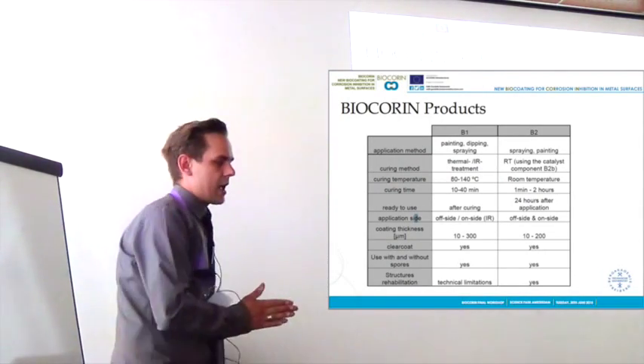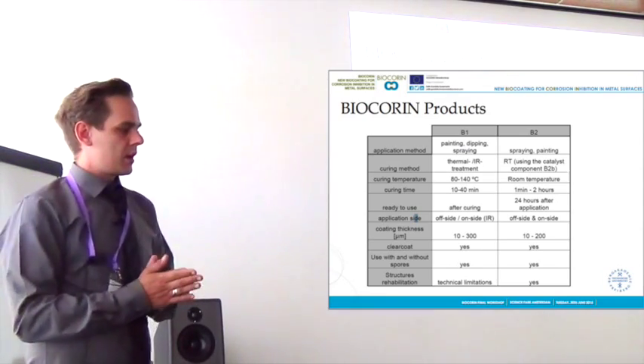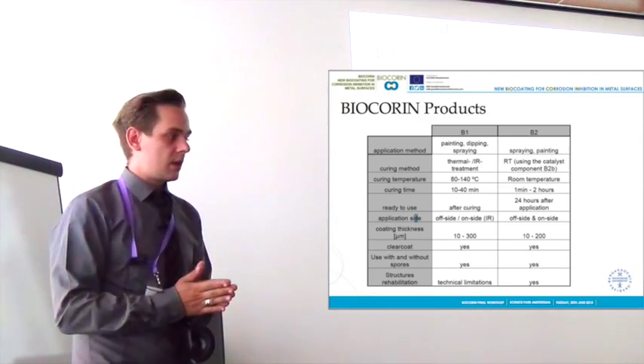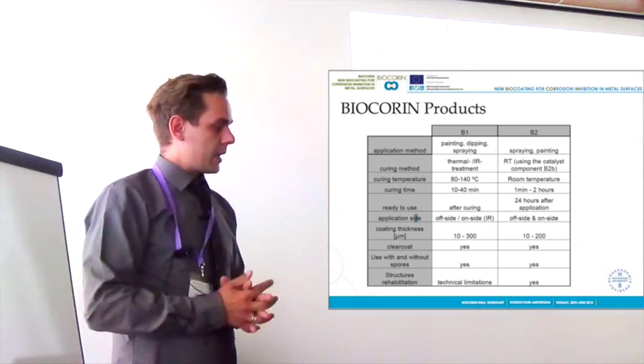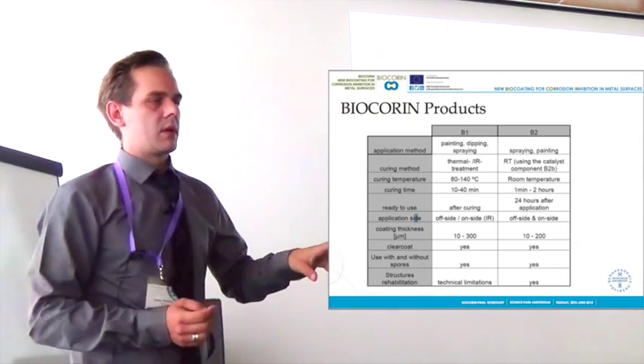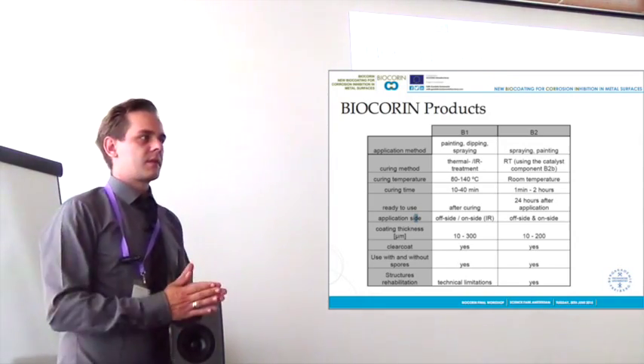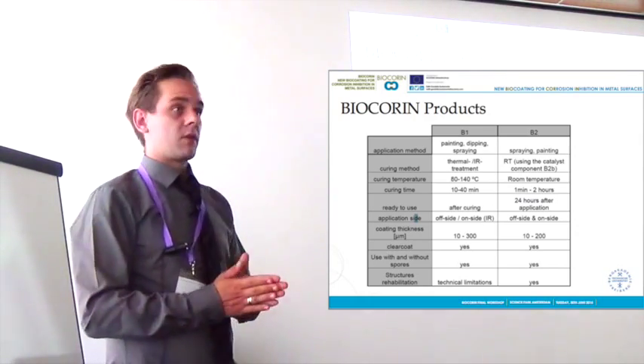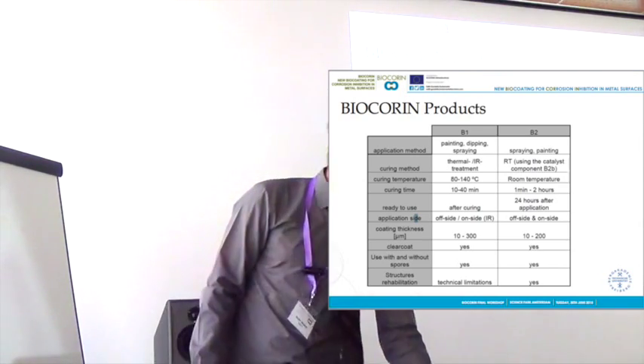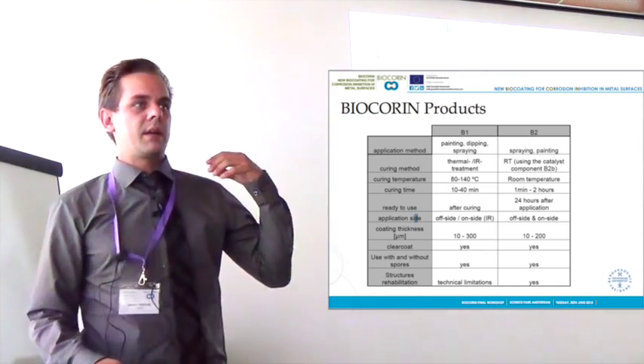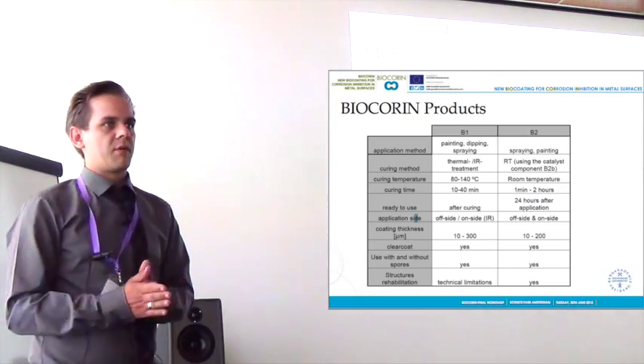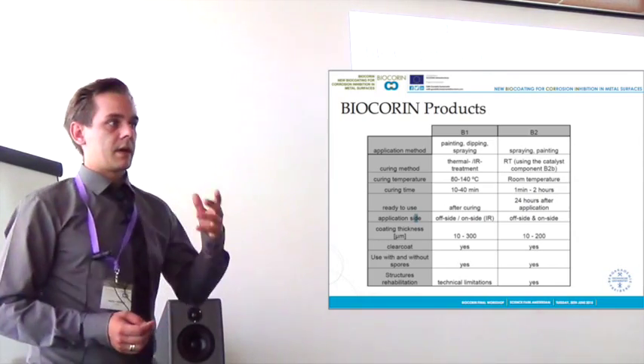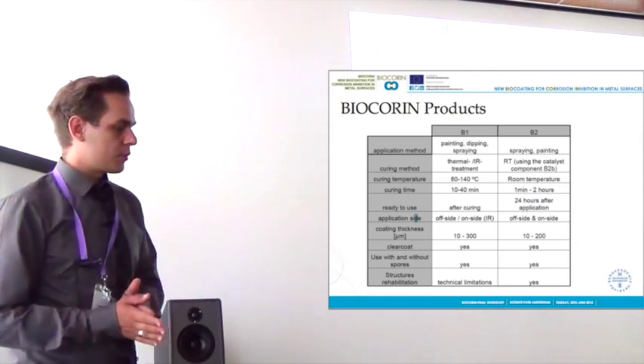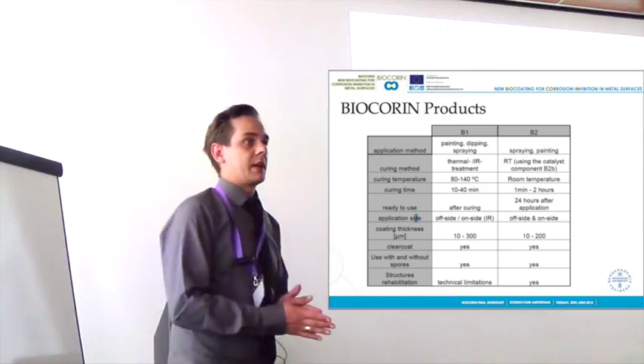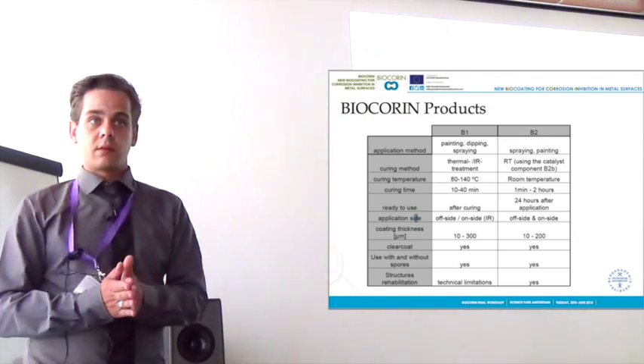So we have two main sol-gel products. B1 is an oven-cured material, and B2 is a room temperature curable material. Both materials are very similar in composition. The main difference is the amount of cross-linked siloxane in the materials. As you can see, both materials can be applied in very high thicknesses. The oven-cured material can be applied in higher thicknesses. This has something to do with the evaporation rate of water and other solvents that are used for the production process. Both materials can be used as a clear coat. That means you don't have to formulate them. You can, but you don't have to.